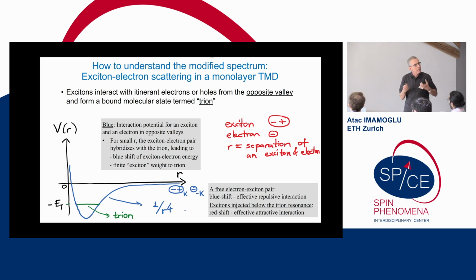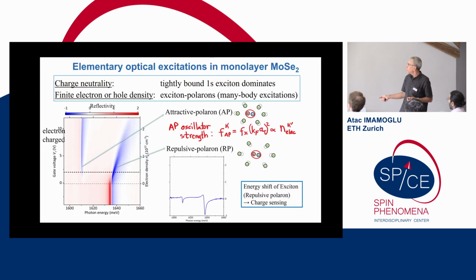That is a generic scenario: whenever we look at the scattering states of two particles in the presence of a bound state, they will act as if they have effectively repulsive interactions, even if the potential is attractive. On the other hand, the bound state, which doesn't have any optical oscillator strength, through the hybridization with the scattering state picks up an exciton character, and it redshifts while picking up oscillator strength. And that's essentially why we have these two resonances in the system.